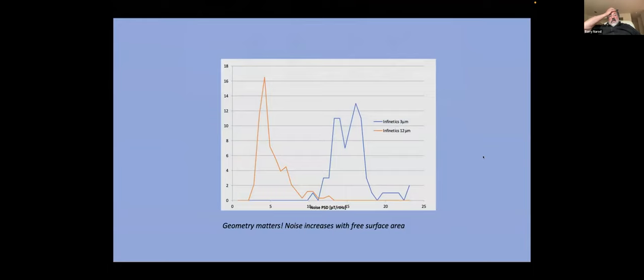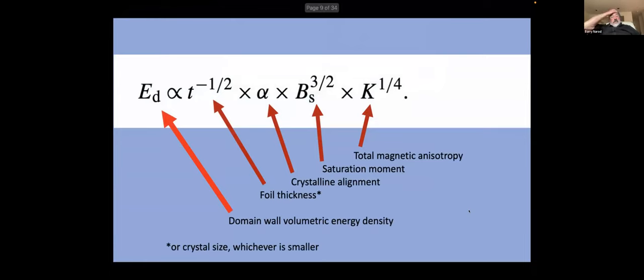So here are some noise data from two sets of legacy Infinetics rings. The blue ones over here are rings in which the foils are 3 microns thick, and the red ones over here are rings in which the foils are 12 microns thick, and all other parameters have been kept the same in these ones. But here you can see that the thin foils, which have four times as much surface area, have four times the noise of the rings that have the 12 micron foils. So noise is very much controlled, at least in one parameter, by the surface area available, which is not exactly a magnetic property, simply surface. Okay, so back to this equation.